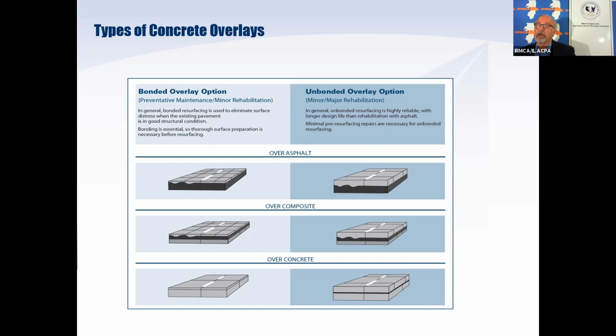The overlay on the left, we have built those anywhere from 2 inches to 6 inches. On the right-hand side, when it's unbonded, we are essentially constructing a new concrete pavement on an existing asphalt base. That pavement may be 9 inches, 10, even 11 inches thick, whereas the one on the left hand is probably more in the order of 4 inches, even for fairly heavily trafficked roadways.